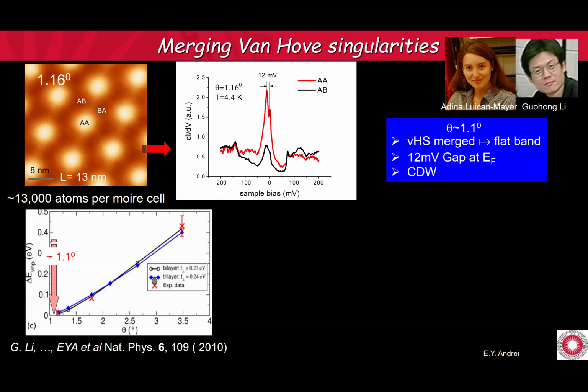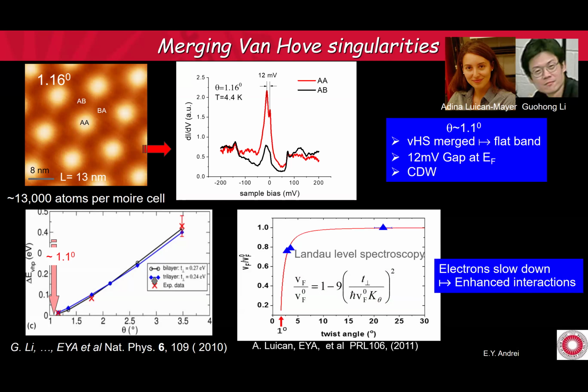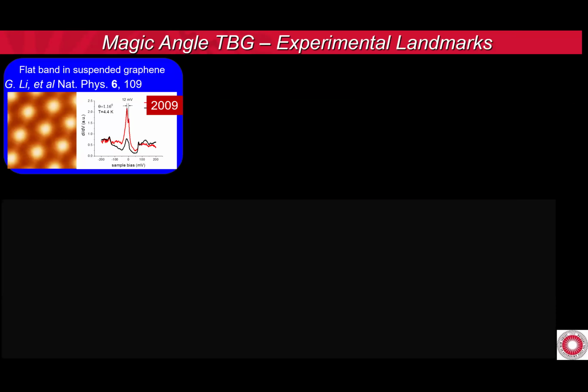So this is the Moire, and this is the van Hove singularity separation as a function of twist angle. It kind of goes to zero by the time we're at 1 degree. We didn't understand this very well at the time, but we had theory help. And then we could measure the Fermi velocity using Landau level spectroscopy. You see the Fermi velocity comes down as you approach this magic angle. So the electrons slow down, as they're supposed to if we have a flat band. Okay, so this was back in 2009, and as somebody mentioned here, there was no control on the substrate. We couldn't control the twist angle.